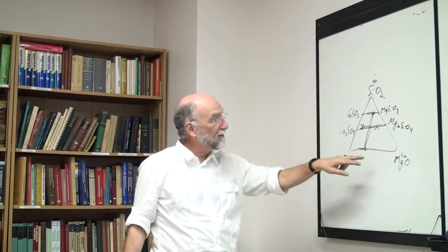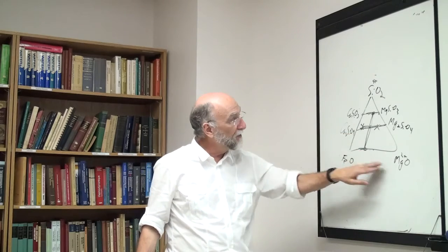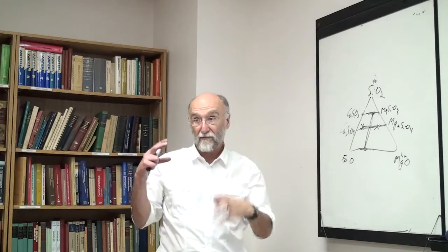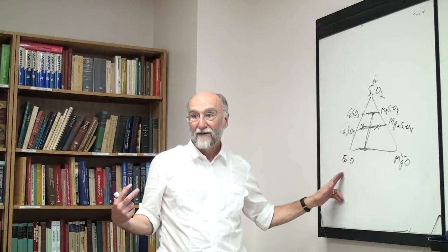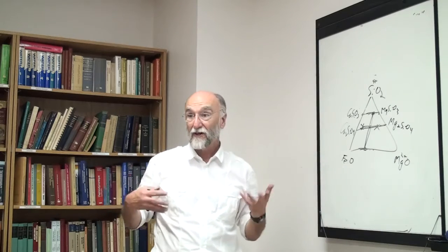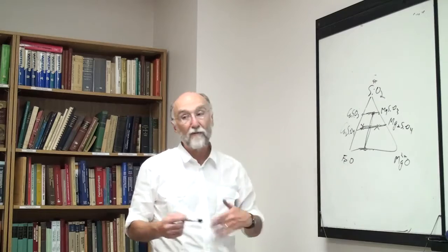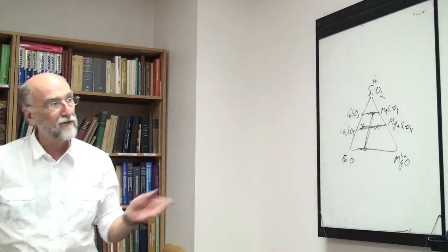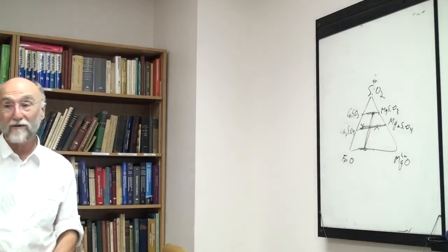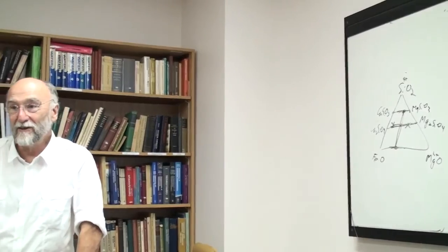Or you can see the diagram sometimes in equilibrium with iron. So you have this slag FeO-MgO-SiO2 in equilibrium with a metallic phase. That fixes the activity of iron. So it does look, again, like a ternary diagram, because all phases in equilibrium have the same activity of iron, just like they have to have the same PO2. But I'll show you this next week. This is where these things can get kind of complex, especially if you have 4 or 5 oxides. How do you interpret a phase diagram?